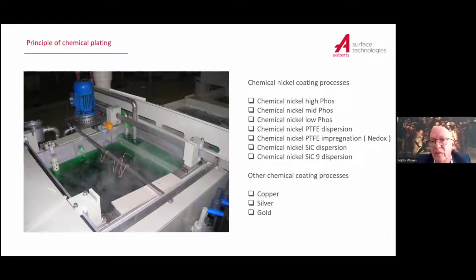You have chemical processes like high phos, mid phos, and low phosphor. That means that these processes have an amount of phosphor in them, which is high, middle, and low. Then you have chemical nickel with PTFE dispersion, so that PTFE is in the coating. You have PTFE impregnation, better known as NEDOX, in which you apply PTFE afterwards on the coating. And you have chemical nickel with silicon dispersion, silicon small particles and silicon big particles. You have some other chemical processes, but they're not so well known in the print industry.